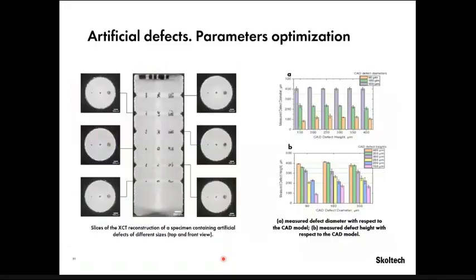Then we checked the printability of these artificial defects, no longer through defects, but with limited size. And we compared it with the CAD model. We used 3 different diameters and 6 heights.